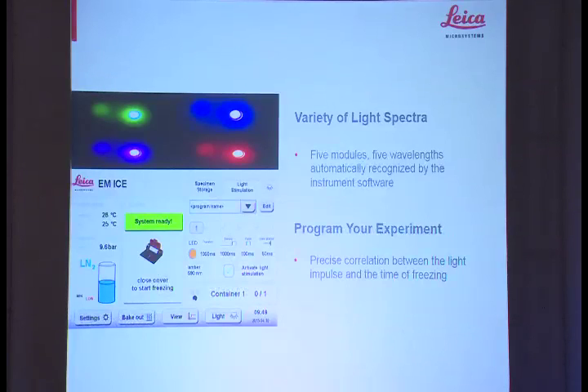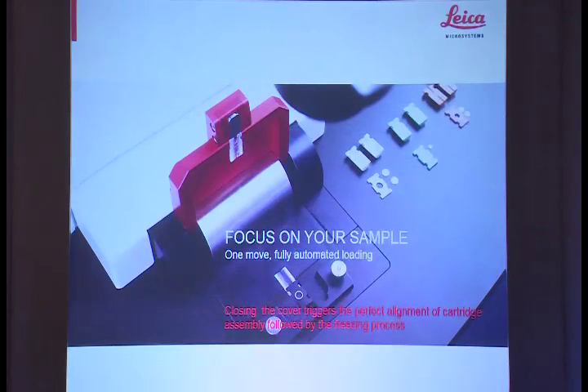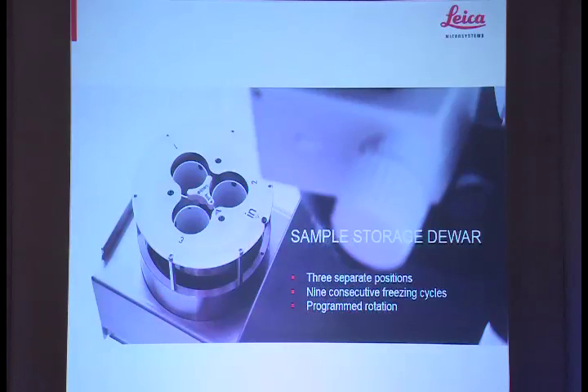But the technique is very, very simple. We insert a light module of a specific wavelength. You can choose the wavelength, and you simply activate the system to give a stimulus of light at a point before freezing, which you can choose. The sample itself is located in a small ring here. So this is the sample carrier. The carrier goes in here. It can be on a sapphire disc if it's maybe a cell culture. And by closing this red cover, it activates the cycle, and it's as simple as that. So high pressure freezing made simple. Close the lid, and it fires away. And your samples drop into these liquid nitrogen cooled containers.